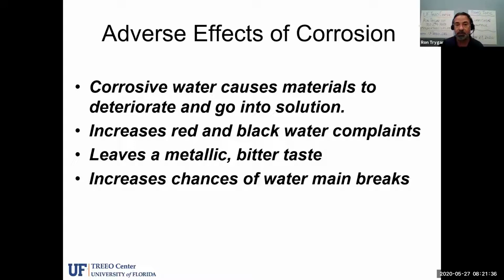So then what happens is we have red water complaints, black water complaints from manganese and some of these other pieces of metal coming off, particulates that get trapped inside the sink aerators or the screens at your homeowners', residents', and consumers' sink faucets. Sometimes the water actually comes out a little red to begin with, especially if the water is corrosive, because that's dissolving some of that iron back into solution, which gives it a little bit of a red tint. The water tends to take on a metallic, bitter taste. It tends to not taste as aesthetically pleasing as water that doesn't have this occurring.